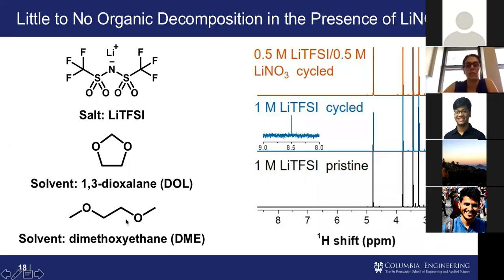So these are the specific ether molecules that we have, this DOL and this DME. We see a little bit of lithium formate formed in the TFSI sample, but it's so small you can't even see it in this spectrum at its original magnitude, showing the DOL and the DME. I had to blow it up and show it in this inset here. So very minuscule amounts. We don't see any of this in the case where the nitrate is present.